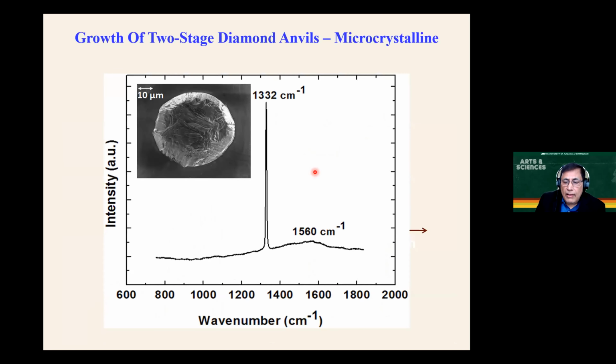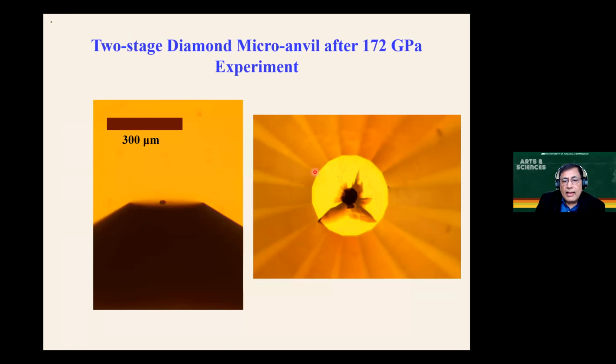However, what we find is that the diamond indeed fractures in these experiments. I mean, it doesn't show bulk fracture, but there are cracks. And very interestingly, it's not the nanodiamond which actually fractures, but the underlying single crystal diamond.